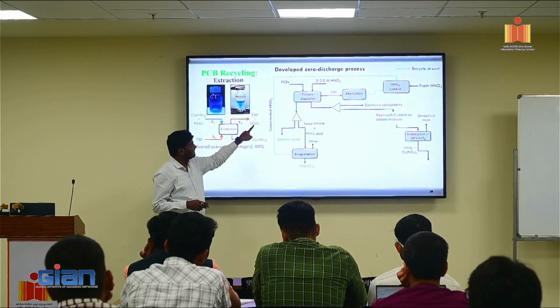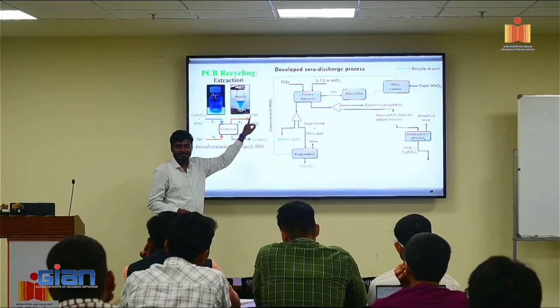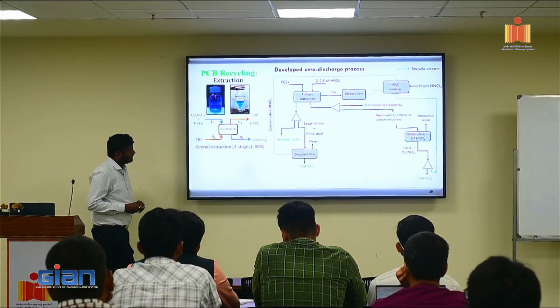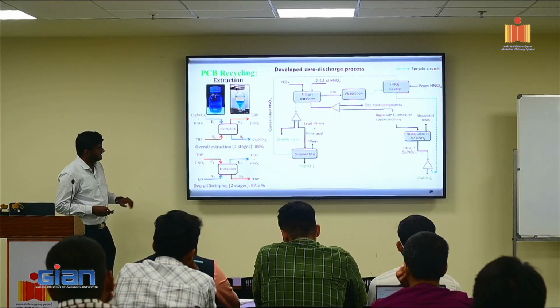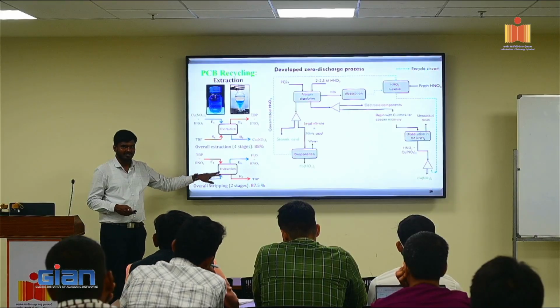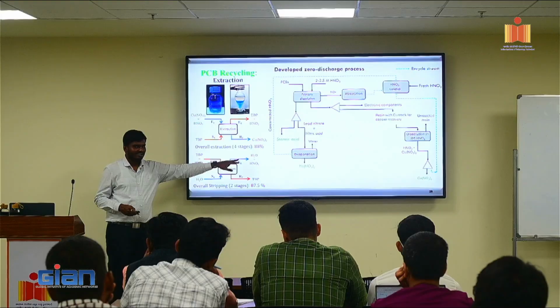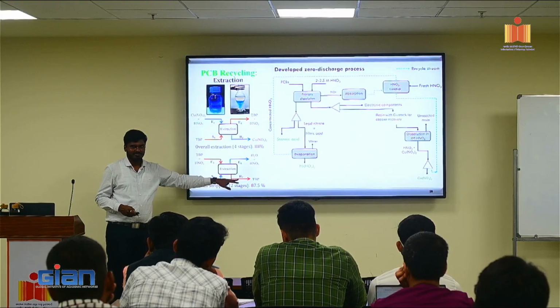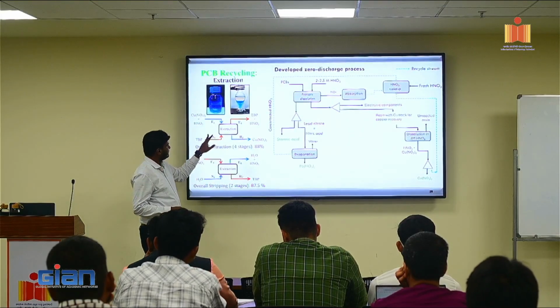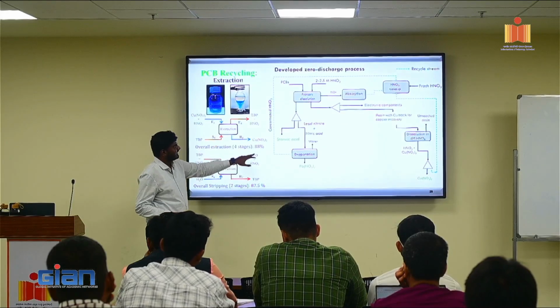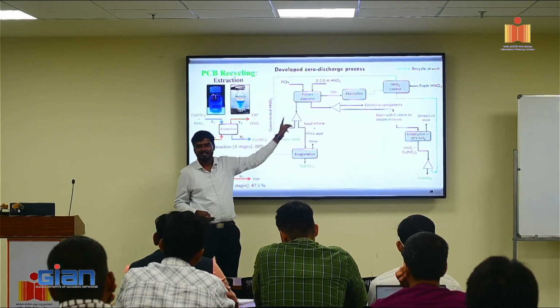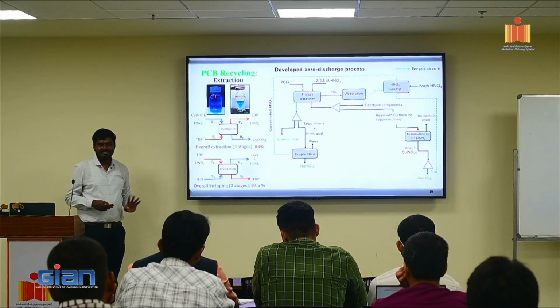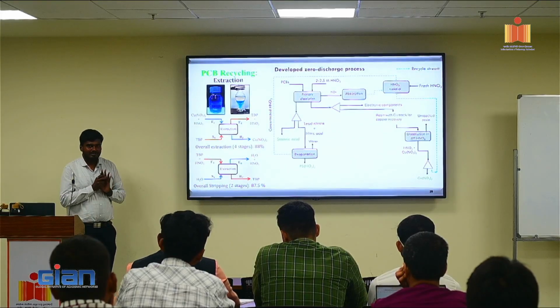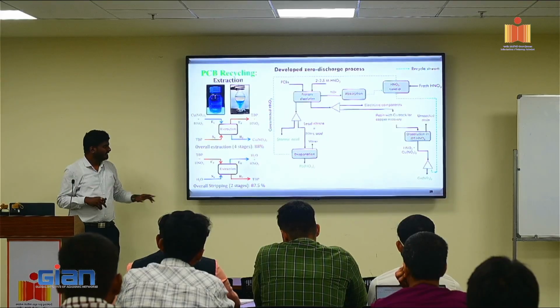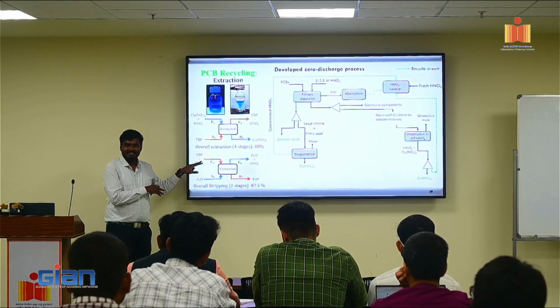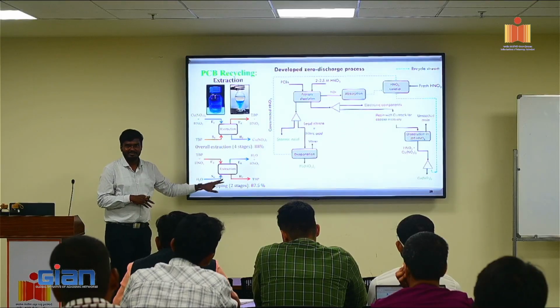Now this stream is there, right? I have to separate this TBP and nitric acid again. So how did we do it? We added an additional step called stripping. When you introduce water, this water will take all the nitric acid and you get a pure stream of TBP. This TBP can be reused again here, and this dilute nitric acid can be mixed with HNO3 makeup and be reused. So this is clear, right? So basically I'm trying to separate nitric acid and recycle it. And this TBP, though I am buying it, I am trying to recycle as much as possible.